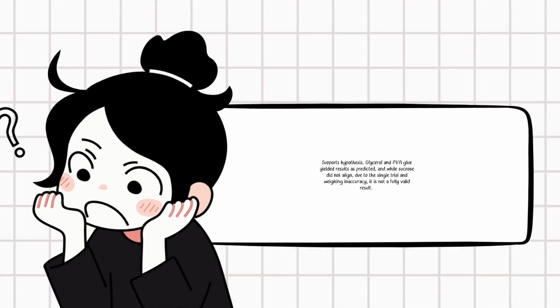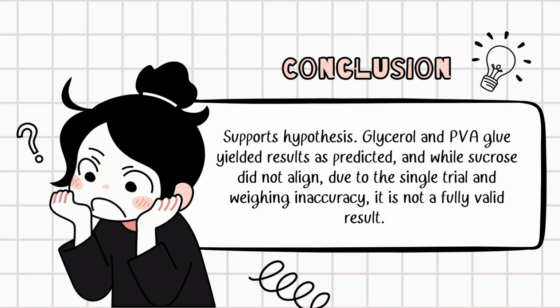In conclusion, this experiment confirmed that additive composition significantly affects bioplastic properties, overall supporting the hypothesis. Glycerol increased flexibility, scoring a 5, but lowered tensile strength to a 1.5 as predicted. Adding PVA glue maintained a high flexibility at 4, while improving tensile strength to 3, aligning with the hypothesized range once more.